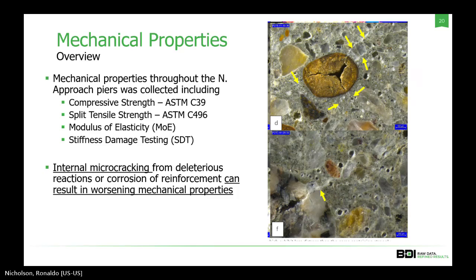All right, so for the mechanical properties, again, we did compressive strength based on ASTM C39, split tensile based on ASTM C496, and modulus of elasticity and stiffness damage testing, where naturally the internal microcracking from these types of cracking and expansion can result in worsening mechanical properties. So we wanted to make sure that we were testing for those for the repair design.